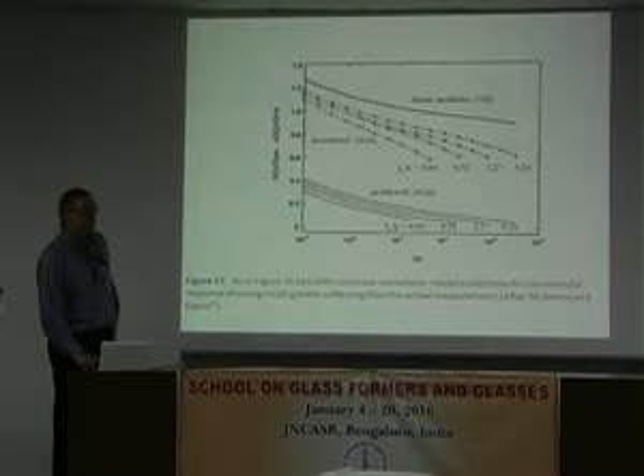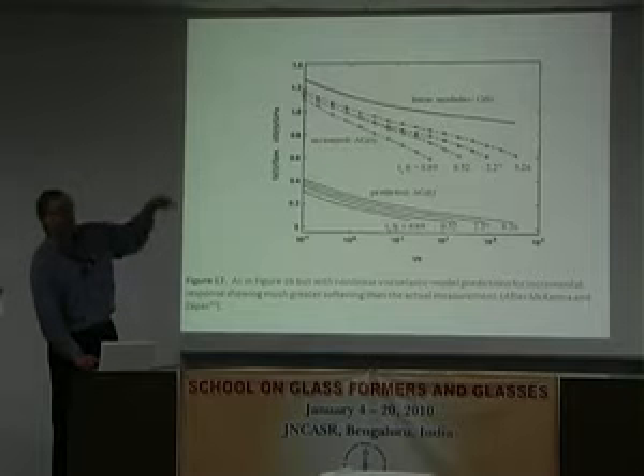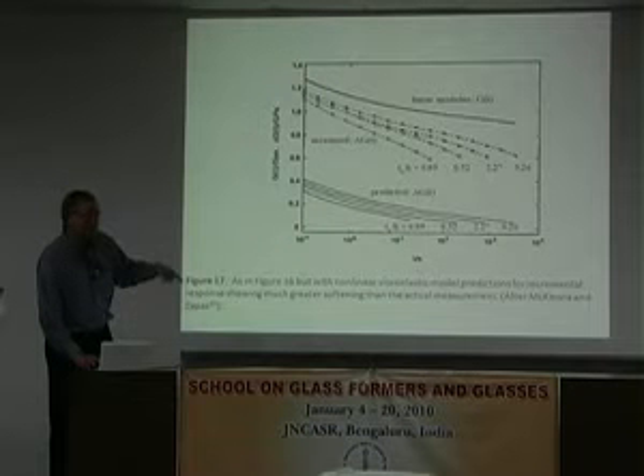We measured it. Phi prime, we were able to measure, because it's just an isochronal modulus. We had to run experiments up to those strains, but once you do that strain, you know the modulus. So phi prime is directly measurable. Without doing that experiment, we did a series of single-step stress relaxation experiments.